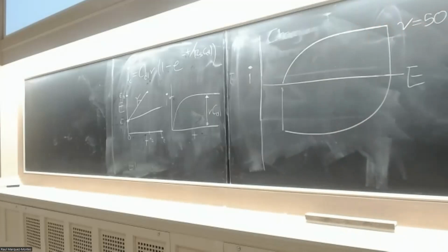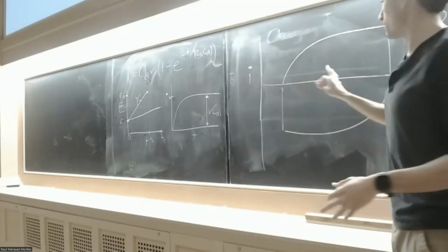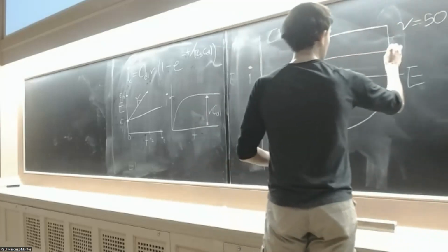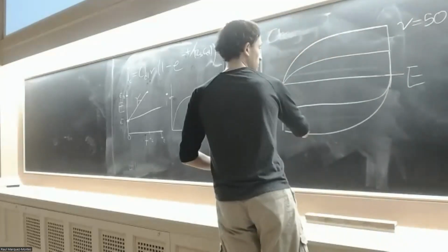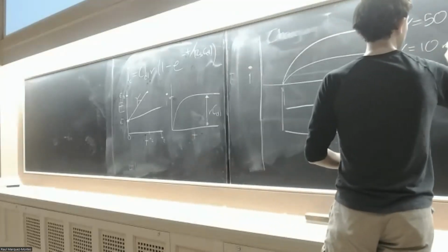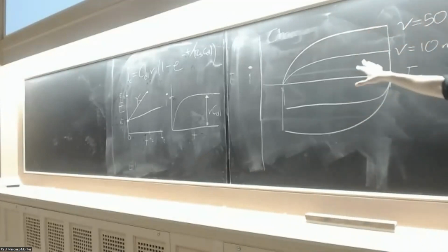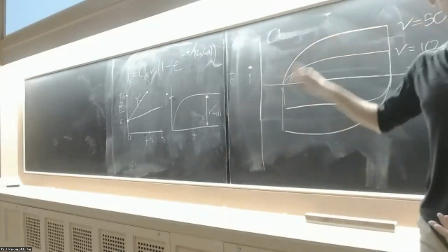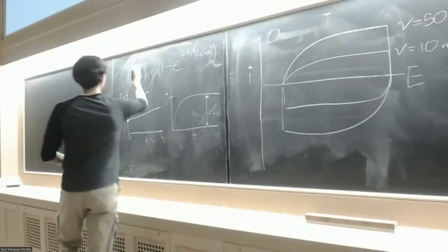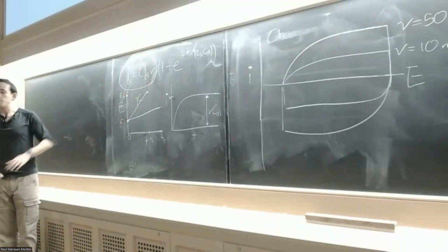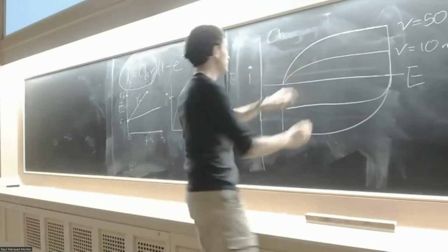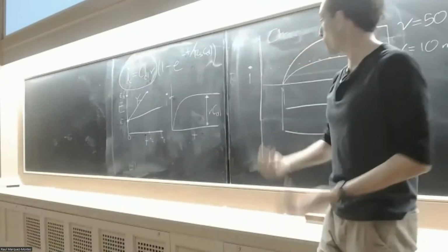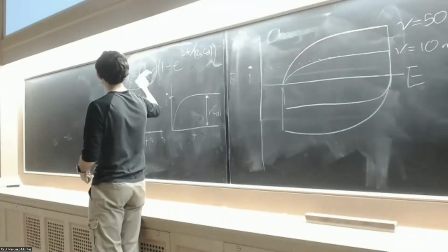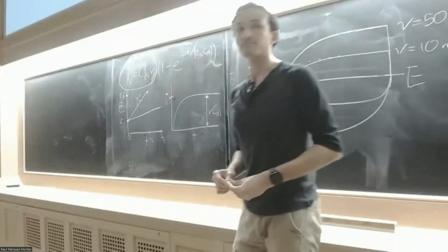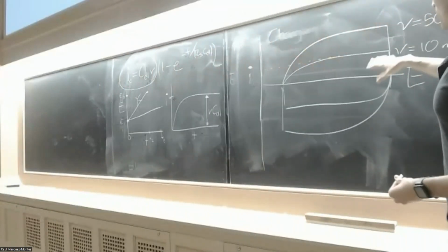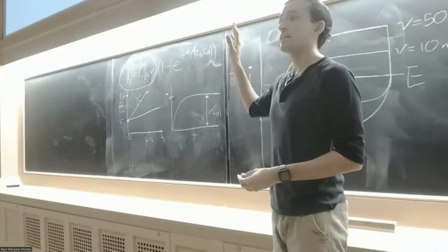It turns out that if we change the scan rate, like if we scan the potential maybe at 10 millivolts per second, we will see something like this. So this means that this current is proportional to the scan rate. And actually it's true, because in this equation we can see that the charging current is proportional to the scan rate. So if we increase the scan rate, we should see a higher charging current. And therefore, we can use this relationship to get the double layer capacitance.